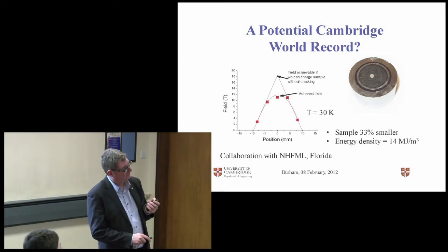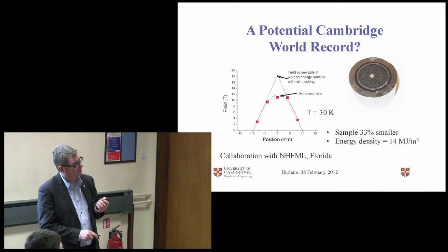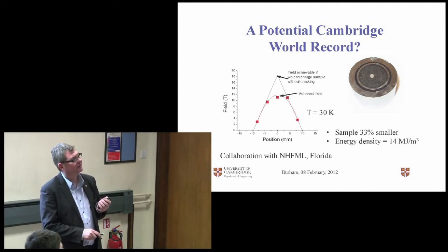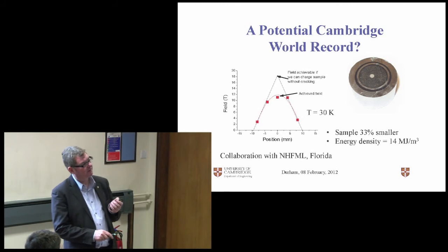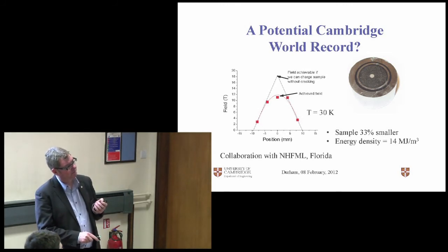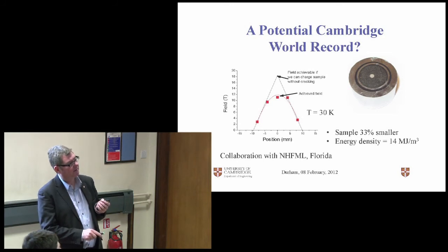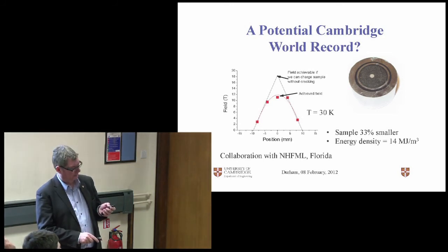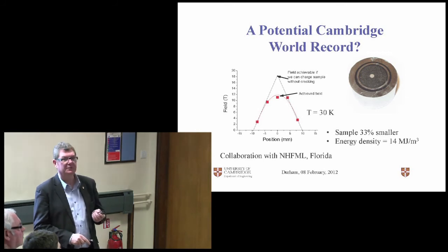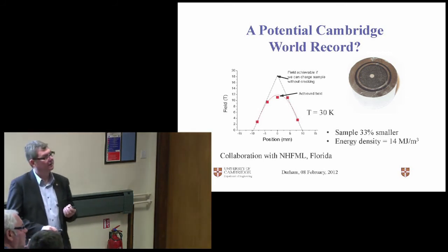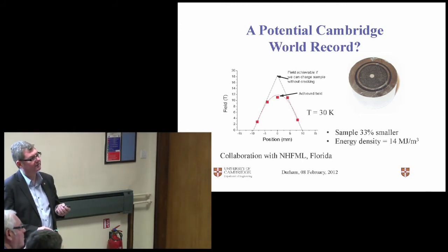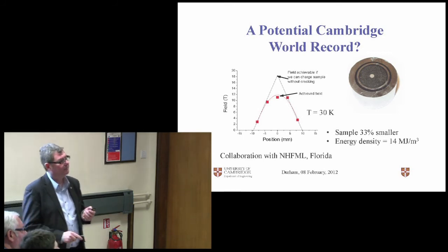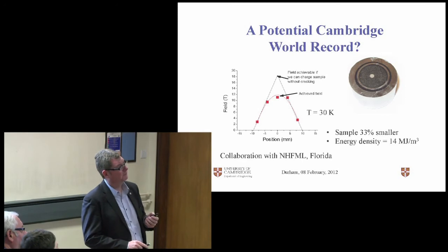So our 3 Tesla field, the red dots, was our sample. This is the sample we used, and it is now up to 11 Tesla at 30 Kelvin. This is a stainless steel reinforced sample. Here's our silver heat leak, and here's our bulk sample. And this particular sample is 33% smaller than that used by the Japanese, so the energy density is probably a record energy density already. But this sample failed mechanically, and we've already worked out how we can reinforce it.